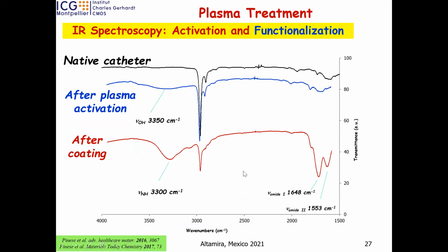Yeah, we characterize this catheter before, as received. After plasma activation, you can see there are some SiOH groups. You have this large band around 3,000 centimeter minus 1. And what is interesting, after coating with peptide, you can see clearly the part of NH of peptide is very huge, even the carbonyl. And the skeleton of the catheter becomes minor. So that means you have good functionalization on the surface of our catheter.